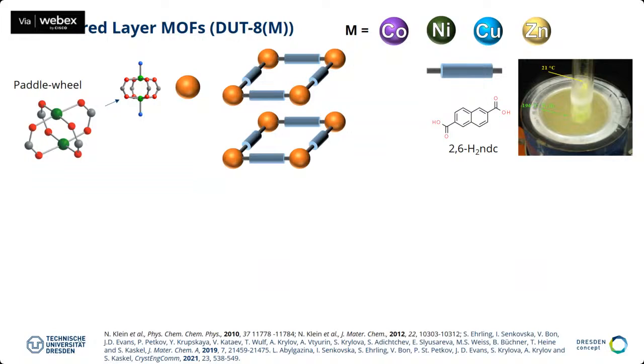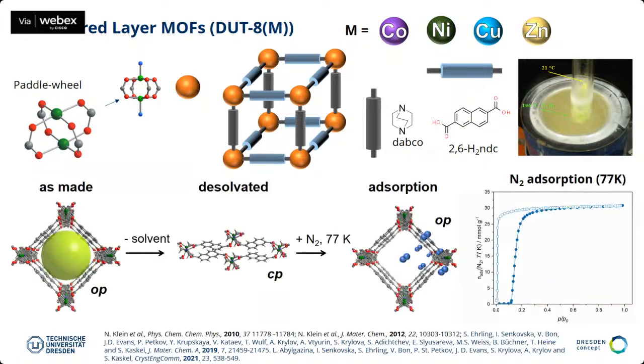So initially you form these four rings. This is very similar to constructing a building. First, you have square grids to form the different stories, and then you also need a pillar, and the pillar in this case is the small molecule DABCO. This is the material which shows a huge volume change. First, when you synthesize it, it has the open pore structure, but when you desolvate it, when you pull vacuum, it transforms into a contracted porous phase.